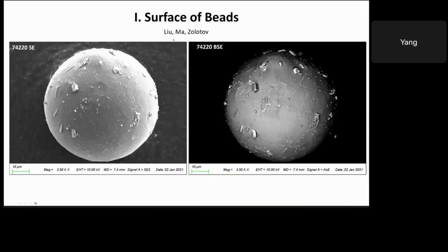Those are the group of us involved in that study. Here is an example comparing secondary electron versus backscattered electron images. Secondary electron images give us mostly the topography, where bright features are usually higher relief compared to darker features. On the other hand, the backscattered electron image gives us more average composition information. When something is brighter in BSE, it's denser, heavier in terms of its average atomic number, compared to darker material in BSE. In the subsequent slides, all the images are backscattered electron images unless specifically noted.